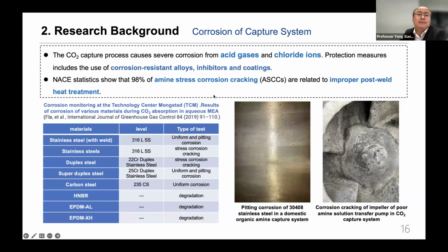So in these systems, we have a lot of corrosion problems. Here we have a reference to see these problems. They have uniform corrosion, they have pitting, but they also have another very big issue, that is stress corrosion cracking, also called SCC. Here we have a picture taken from a CO2 capture power plant. You can see some cracking. That might be SCC, but we are not sure. We are doing some research work to make sure why this crack happens.